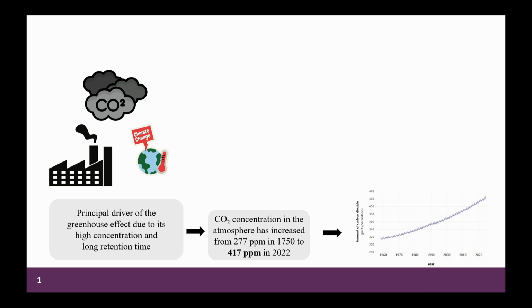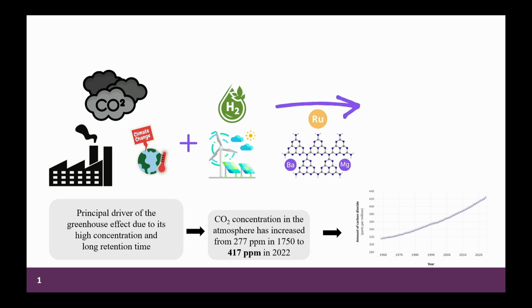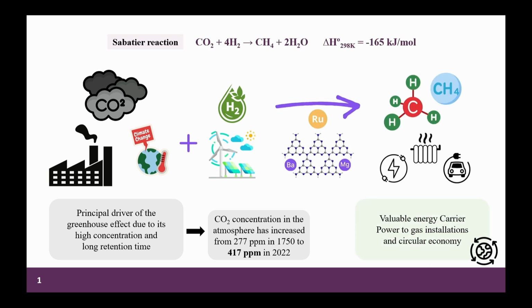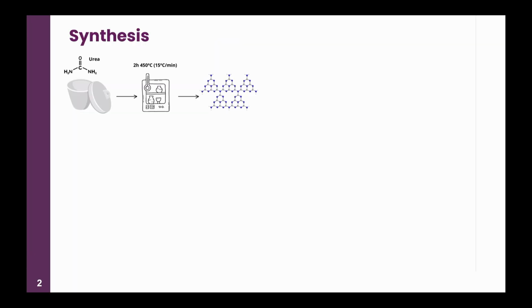As you already know, the increasing concentration of carbon dioxide in the atmosphere due to anthropogenic activity is raising air temperature and causing global warming. That's why great efforts are being made to use renewable energy sources to transform CO2 into value-added products. In this case, using ruthenium-based catalysts to transform CO2 into methane, which is a valuable energy carrier. The graphitic carbon nitride, or C3N4, was prepared by thermal polymerization of urea, and then 1% of ruthenium was incorporated by incipient impregnation to give the undoped catalyst.